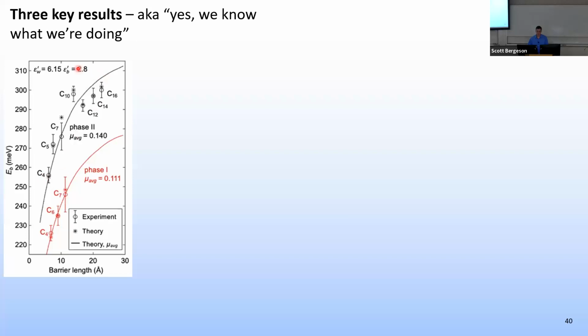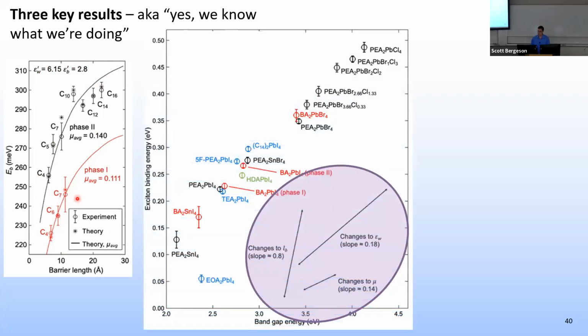And we fit this data to give us these dielectric constant values, but then using these values, we looked at a different structure of these perovskites, a different phase, and with no additional fitted parameters, we were able to exactly predict what these binding energies should be. So we think that we do know what we're doing.